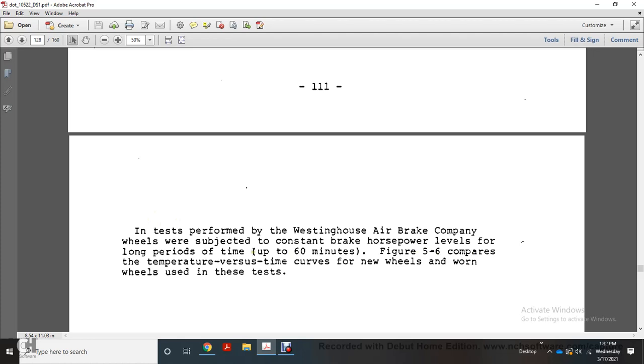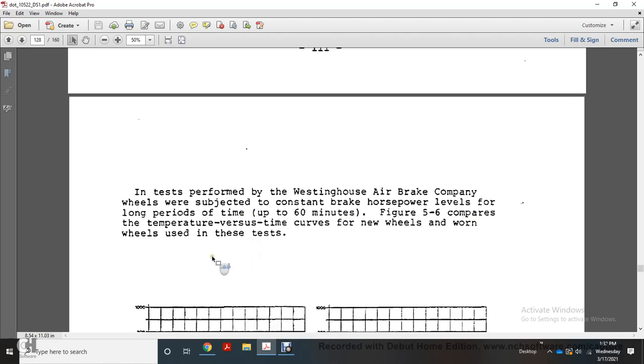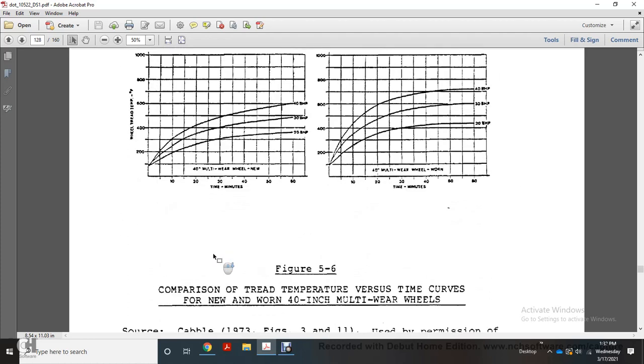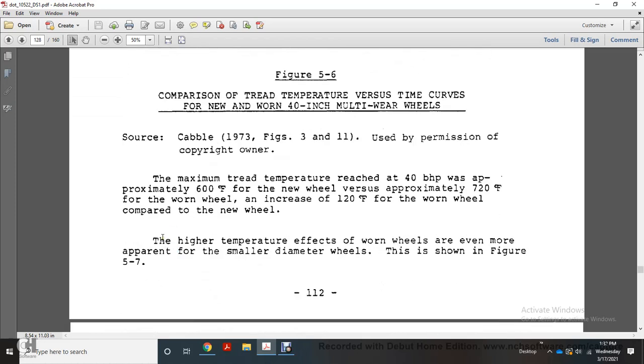Figure 5.6 compares the temperature versus time curve of the new wheels and the worn wheels. Figure 5.6 shows the time in minutes, wheel tread and temperatures. Maximum tread temperature reached at 40 BHP is approximately 600 degrees Fahrenheit for the new wheel versus approximately 720 degrees Fahrenheit for the worn wheel, an increase of 120 degrees Fahrenheit.